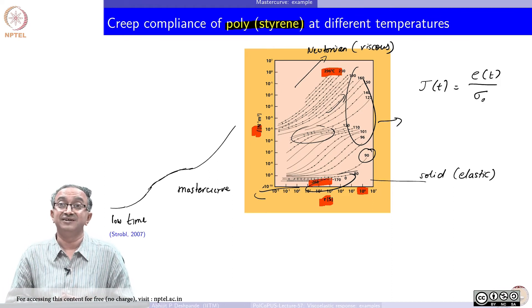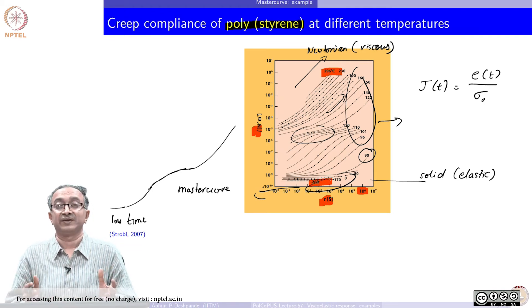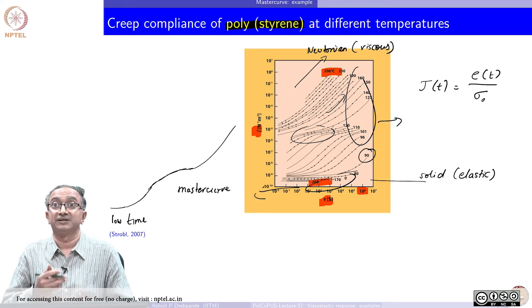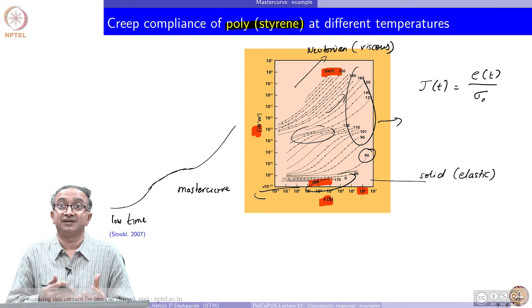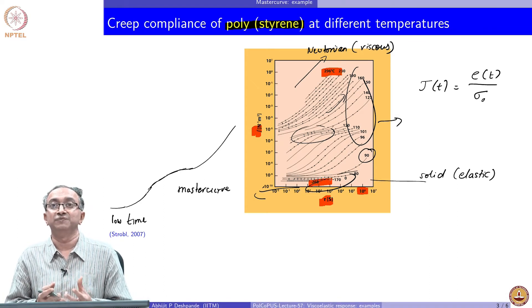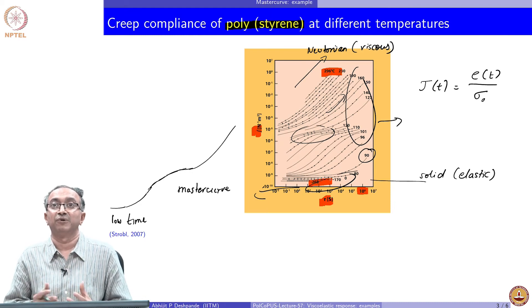we may require thousands and millions of years for it to actually start flowing. And that is again the concept of Deborah number that we talked about that the material relaxation time and the experimental times, the relationship between the two we will have to look at while analyzing elastic response of polymeric materials.